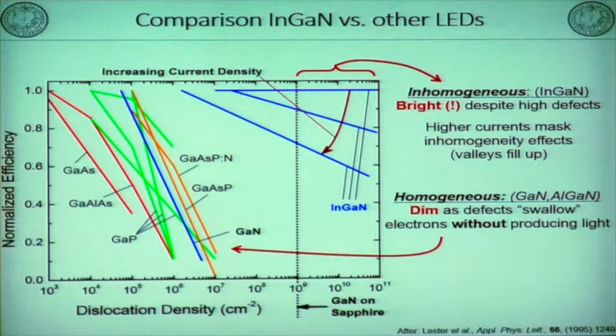So indium gallium nitride is a key material. This shows the efficiency of various LEDs as a function of dislocation density. Dislocation density is the crystal defect density. You can see conventional compound semiconductors such as gallium arsenide, gallium phosphide, and gallium arsenide phosphide LEDs. For those LEDs, the efficiency becomes very small when the dislocation density is more than 10 to the third or fourth. But in the case of indium gallium nitride based LEDs, the efficiency is still very high, even when the dislocation density is on the order of 10 to the 9th. So indium gallium nitride is a key material to make highly efficient LEDs in spite of the huge number of crystal defects. Because 10 to the 9th is a crazy number of crystal defects.